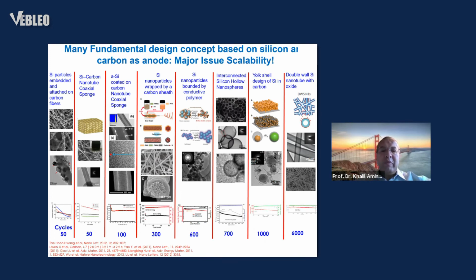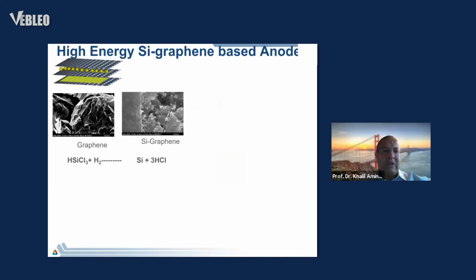At Argonne, we developed a new technique where we use a gas, because gas can go everywhere. Again, so to incorporate the silicon in graphene, dissolve the graphene that is basically exfoliated using acid. The advantage here, we use trichlorosilane, a very low cost material that is used for the silicon wafer. It's about $8 a liter. The idea is to basically reduce this once it goes inside the graphene sheet and form silicon like this.